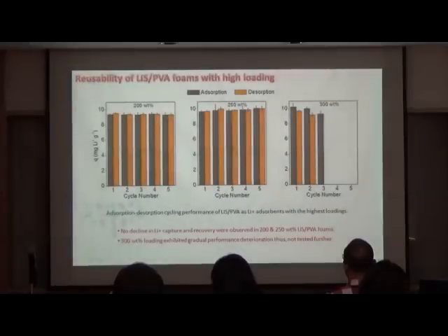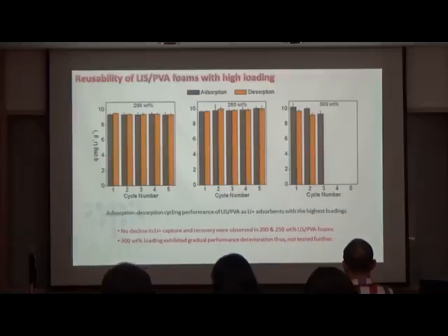And then, for the reusability of LIS-PVA foams with high loading, while the composite foams with the highest LIS loading exhibited the best lithium adsorption, the extremely low fraction of PVA means fewer sites for cross-linking, which could compromise the durability of our foam samples. Thus, the performance of foams with the highest loadings was evaluated through a cycled adsorption-desorption test, while examining their mechanical stabilities through repeated mechanical and flexibility analysis, as shown in these figures. After several cycles, you can see that there is no decline in the adsorption capacity of the 200 and 250 weight% samples. However, for the 300 weight% sample, the foam gradually deteriorated, hence no further testing was done.